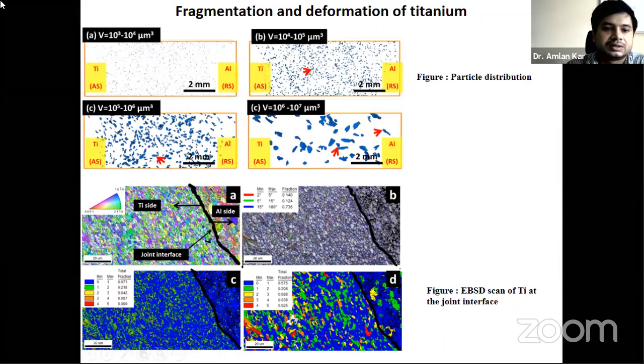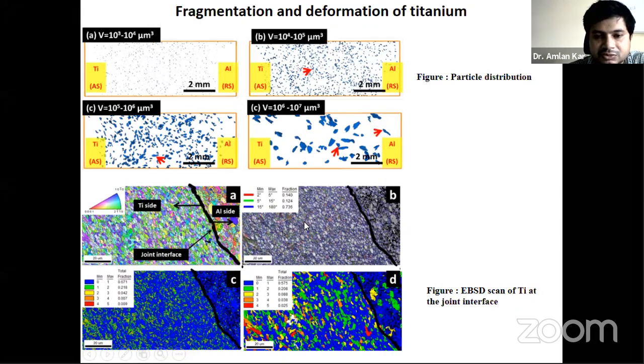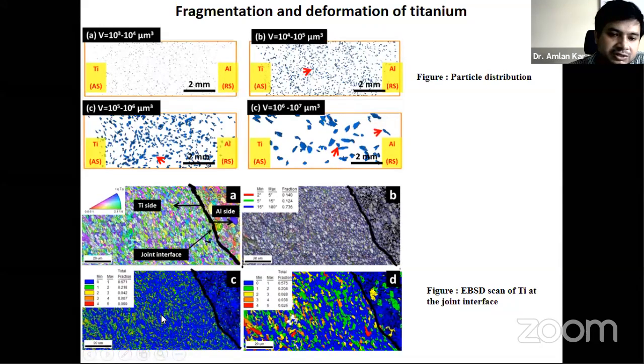Okay, this is the recrystallized structure. You can see different grain orientations, and this is mostly high angle grain boundary. You can see this is a 15 to 180 degrees deviation, so this is high angle grain boundary. And from the KAM map, this actually shows how the dislocation distribution is more or less homogeneous.